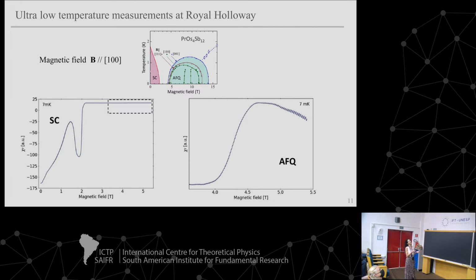So what we see, this is the real part of the magnetic susceptibility as a function of magnetic field, and you can see that the superconducting transition is very prominent, and it's in the right place and everything is okay. This is at 7 millikelvin or so. It looks like nothing else happens in this curve, but if you zoom in on this flat-looking part up here, then you can see that the antiferroquadrupolar phase boundary is also very pronounced.